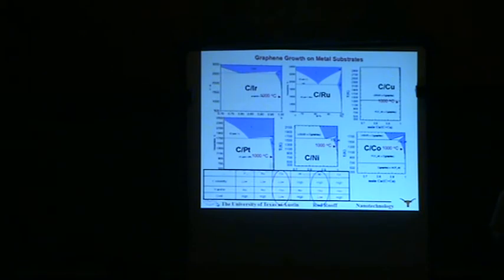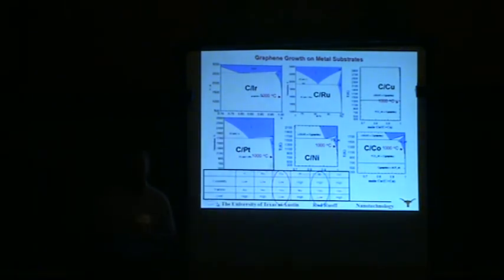So we start with copper foil that might have grain size of just tens of microns that we get from a company, etc. And if you heat it up to 1,000 degrees C under vacuum or inert environment like argon gas, you can get centimeter grains very easily. So you have single crystal regions that are centimeter grains. That turns out not to be true for nickel. Nickel always maintains a relatively small grain size. So it might end up being important to have single crystal regions that are very large to grow graphene. That's still being investigated.